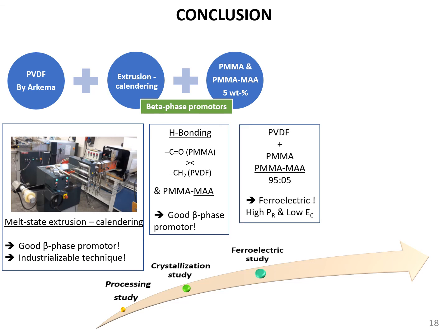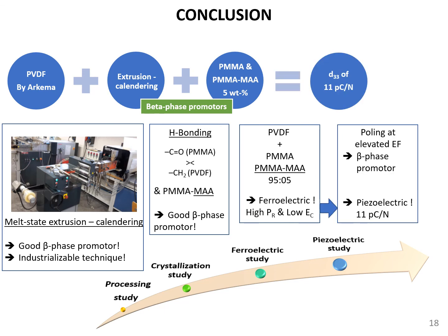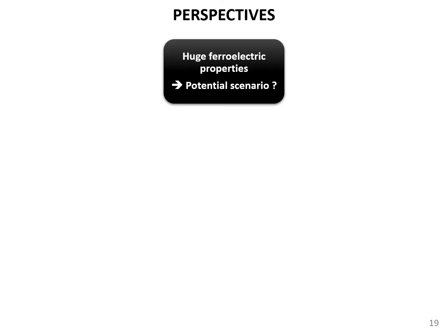Of course, the ferroelectric study is also improved, particularly in the case of the PMMA and the copolymer containing the methacrylate, and that has a very positive effect on the coefficient, the D33, obtaining a value of 11 without any annealing post-processing afterwards. As a perspective, we would like to improve the ferroelectric properties of this blend using different scenarios.